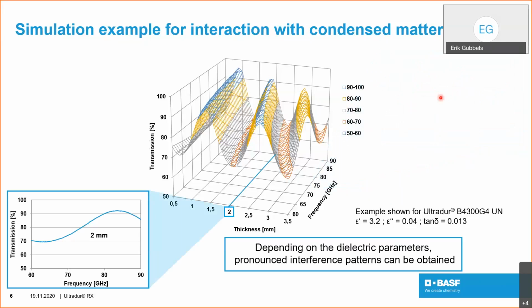If we then look on one thickness and then frequency dependent, you see a similar behavior, although there's only one minimum and one maximum. However, it can be said that depending on the dielectric parameters of a material, but also depending on the thickness, as we just showed you, there can be a very pronounced interference pattern, which needs to be considered.